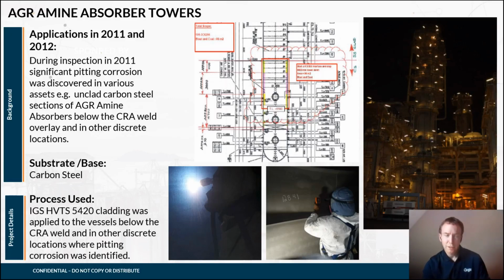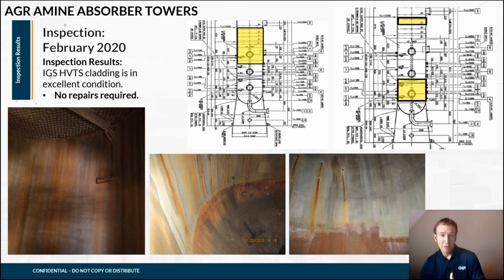So we installed the high velocity thermal spray systems using an IGS technology and an IGS alloy. Those applications were done in 2011 and 2012. These were clients operating in the Middle East. We then went back into these vessels in each subsequent turnaround cycle. So when the original application is done, when you're using a high nobility alloy onto a lower nobility substrate or a non-ferrous alloy onto a ferrous substrate, you can directly measure the thickness of that material. So you can create a map of the application surface and then use that map in future inspections to see if there's been any change to the internal barrier condition.